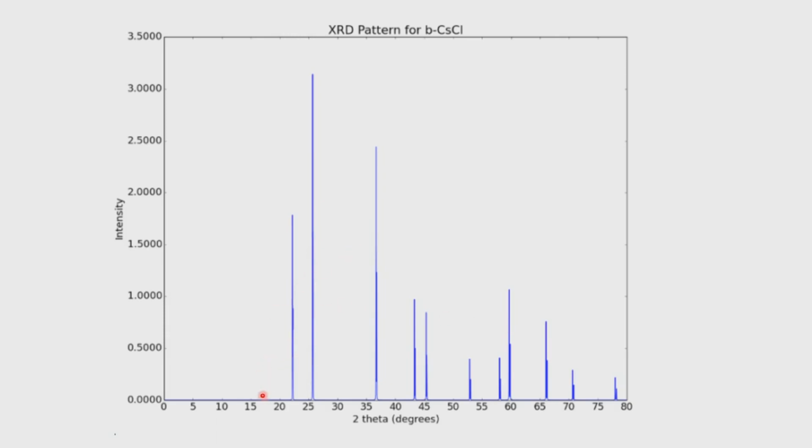In a typical powder pattern, there is a certain width associated with it. This we will all discuss when we go to powder diffraction methodology, which is very crucial, particularly for the pharma industry people, to remember that there will be a certain width with each of these peak positions, and that is very crucial. So effectively, this is the intensity we will get when we put the cesium and chlorine in known positions and calculate the corresponding contributions to individual reflections. So the X-ray diffraction pattern is coming from the planes, and the atoms need not sit in any plane, they can sit wherever they want, but their contribution to the plane can be calculated, just as we have done in the case of cesium chloride.